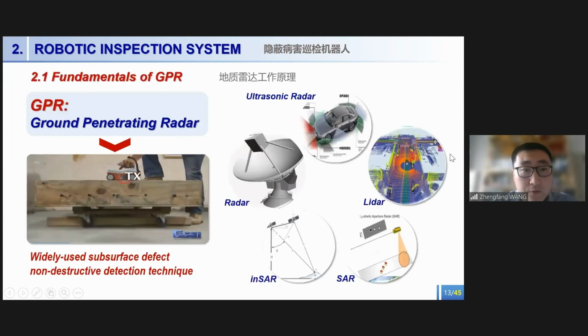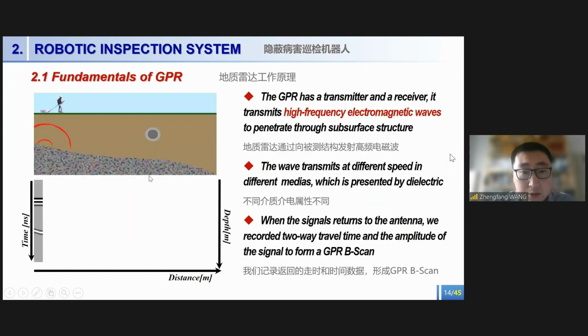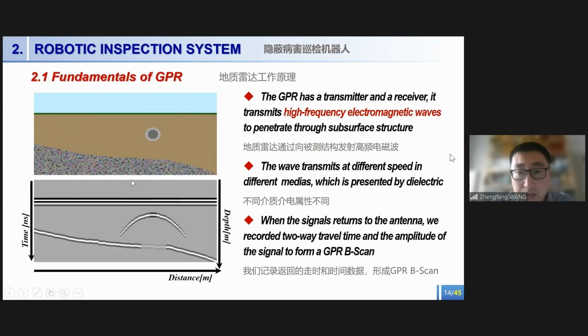I will first introduce some fundamentals of GPR. GPR stands for ground penetrating radar. It's not ultrasonic radar, not LiDAR, not InSAR, not SAR. It's a widely used non-destructive detection technique for the subsurface defects. The GPR usually has a transmitter and a receiver. It transmits high frequency electromagnetic waves to penetrate through the subsurface structure. The wave transmits in different media at different speeds, which is represented by the dielectric constant. When the signal returns to the antenna, we record the two-way travel time and the amplitude of the signal to form a B-scan like this figure. Then from this B-scan, we can interpret what the defects are and where they are. Also, we can reconstruct the dielectric distribution of the structure to be detected.